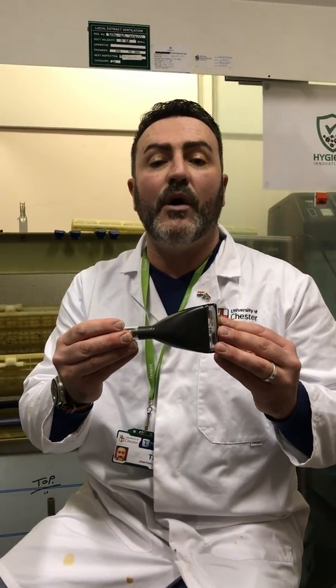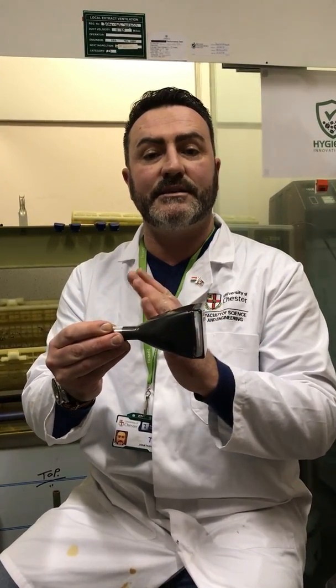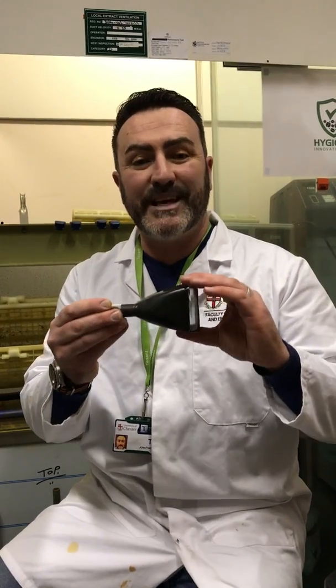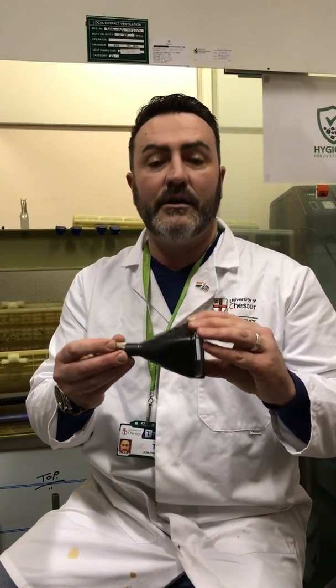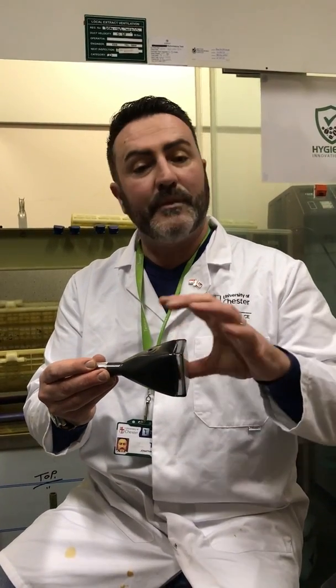Another technology which we invented was to recover the lead from old CRT televisions. This funnel glass contains 20% lead. We chemically dissolve the glass and the lead, recover the lead as a precipitated powder, and also dissolve the glass, making sodium silicate. This sodium silicate then goes into geopolymer. We have another company called Block Walls. You can find us on blockwalls.co.uk, and we currently make 87% recycled geopolymer blocks, which will be 100% recycled geopolymer blocks by 2020. All these technologies are in and around saving the environment, recovering more value, recovering more materials like plastic, and being very, very eco-friendly.